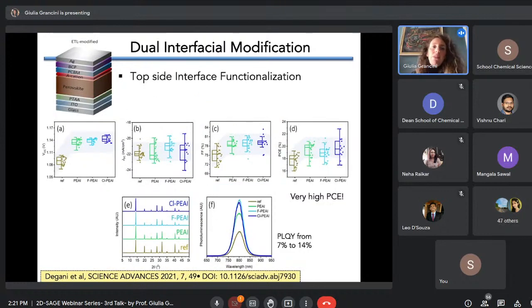What about the top interface? On the top interface, again, you see an improvement in the PCE, which is related to a concomitant improvement in the fill factor and in the VOC, exactly as I told you before. There is the improvement in the VOC. Why? Because the photoluminescence quantum yield increases, because you do have surface passivation. However, in this case, there is no sign, no indication of formation of 2D perovskites.